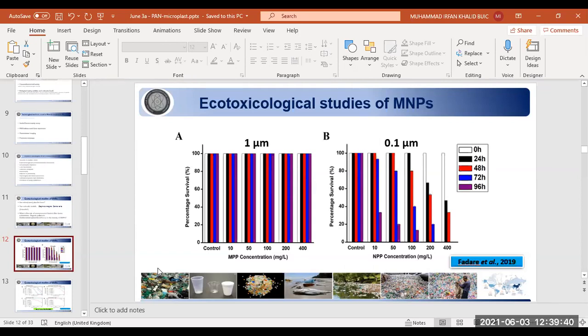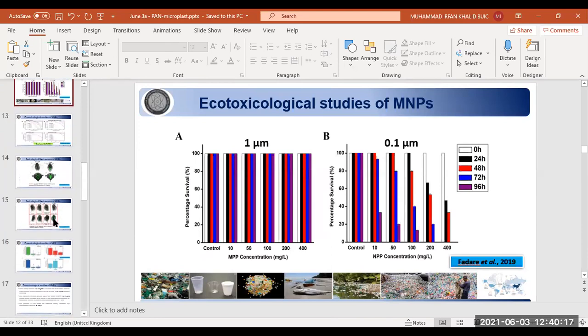Mm-hmm. Well, it's interesting that they're amine coated, because polyamines are known to have quite a lot of cellular effects and possibly cytotoxic effects in drug delivery and all sorts of things. But I'm also interested in the fact that they're polystyrene, which is normally considered to be very hydrophobic. Obviously, once you get a corona on it, it might not be so hydrophobic. But I guess the interesting thing is that it attracts coronas very aggressively because it's very hydrophobic.